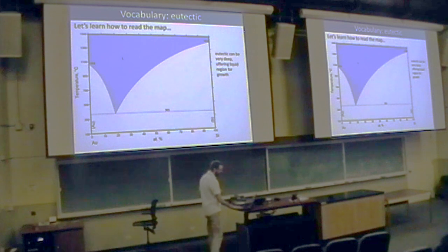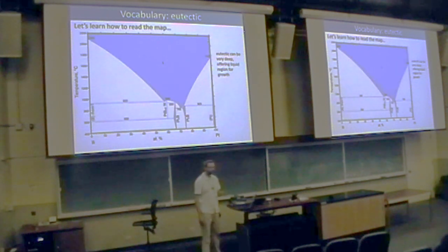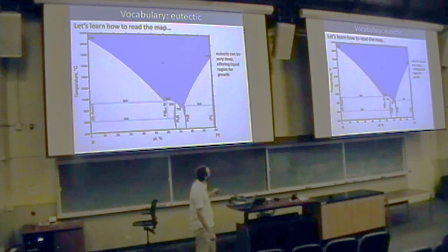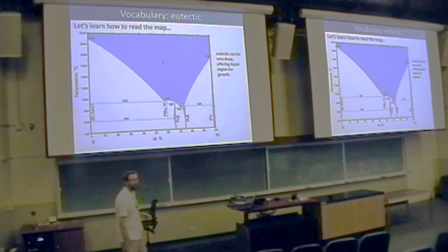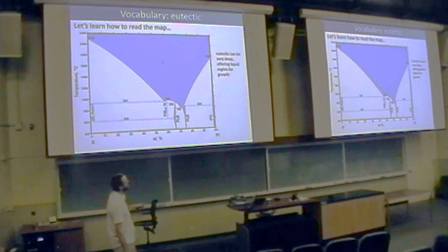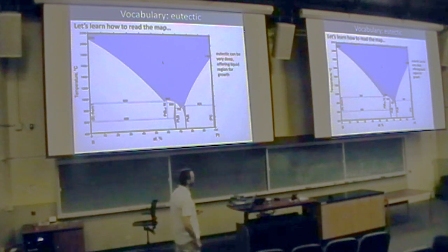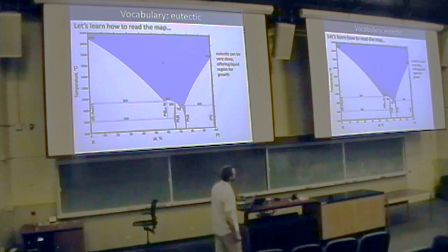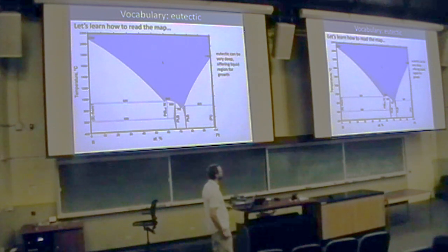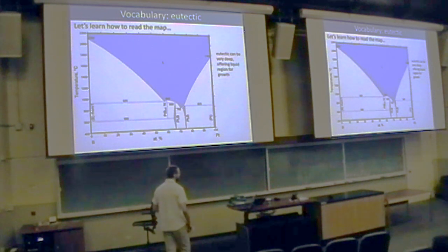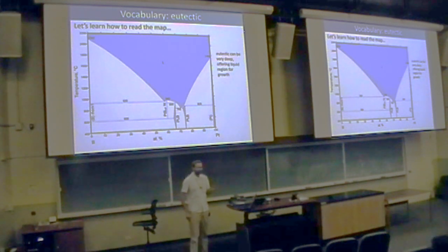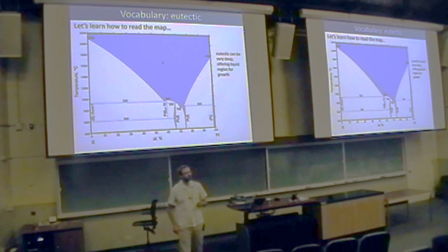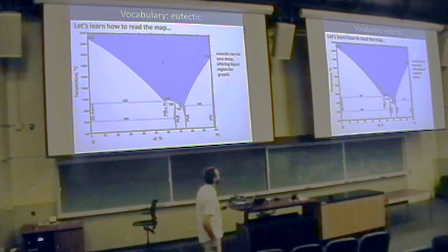And those are very interesting for solution growth, because then we have a huge range of liquid to perform solution growth. Another very good example of this is the system boron and platinum, where these two compounds melt at extremely high temperature, above 1700 degrees Celsius, and there is a quite deep eutectic also on this composition, where they melt below 800 degrees Celsius.